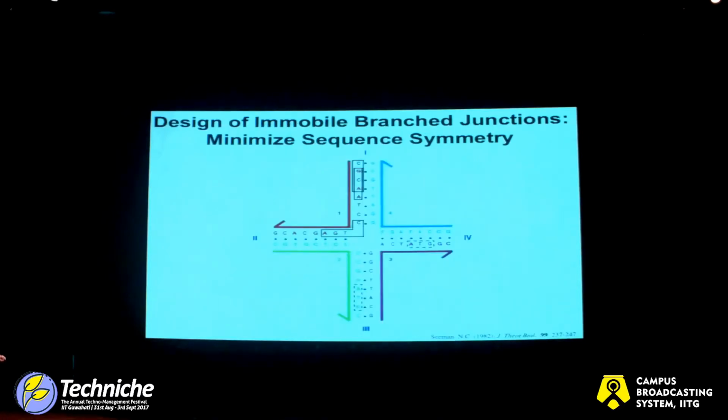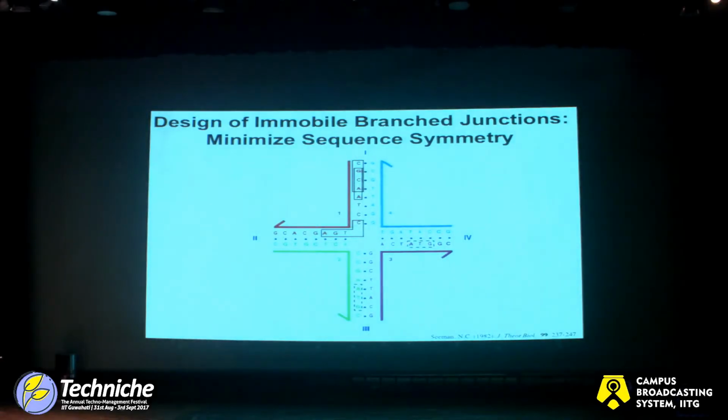Now, it's easiest to look at this system when we draw it like this. So it looks like we have an intersection in a highway. So these are 16 mers of DNA, 4 different strands, 1, 2, 3, and 4. And we've designed the sequences here so that they come together to form this single molecule. I'm not going to go into the details of the design. I'll just say we can do it, and it's rather easy to do. So now we've got a branched molecule. This is analogous to an intermediate in the process of genetic recombination.